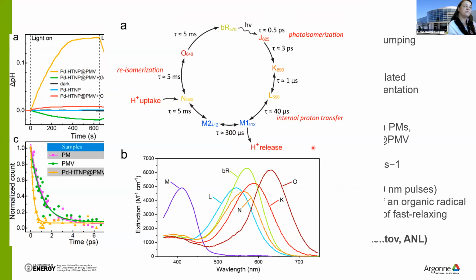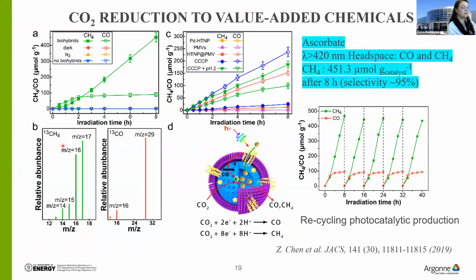So together with our data on inhibitors of proton transfer, we can conclude we indeed observe proton coupled electron transfer in our system. And then we come to the final part of this work, CO2 reduction to value-added chemicals. It's very interesting what we observed.